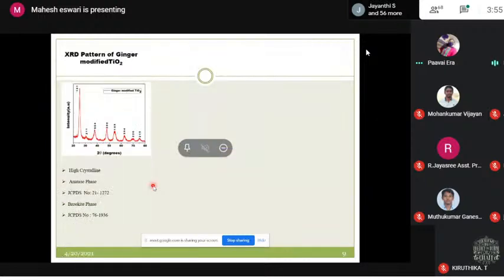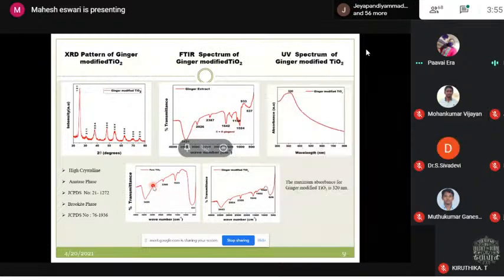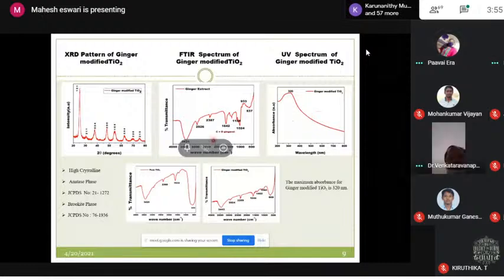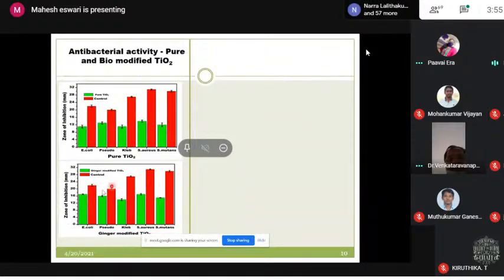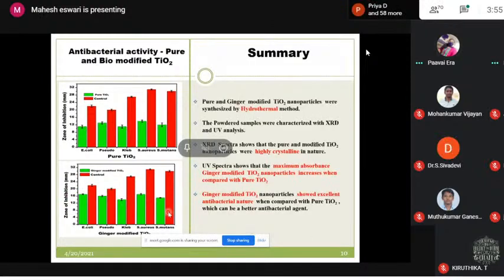Based on that, the XRD pattern analysis, the FTIR spectra and the UV analysis have shown clearly that the maximum absorbance has increased to 320, which clearly shows the ginger has modified the titanium. There is a compound called gingerol, which has a C=O bond, which is around 1642. You can see a clear change here after modification with the titanium dioxide nanoparticles. Now, based on the antibacterial nature, we have seen the enhancement of antibacterial nature due to the modification with ginger. You can see even the gram-negative as well as the gram-positive has attained nearly about 16 to 18 millimeter of zone.